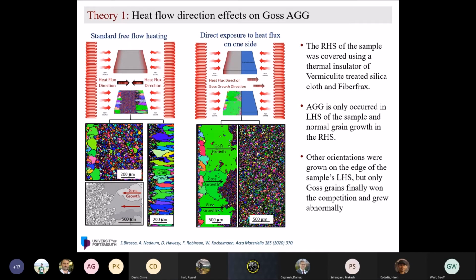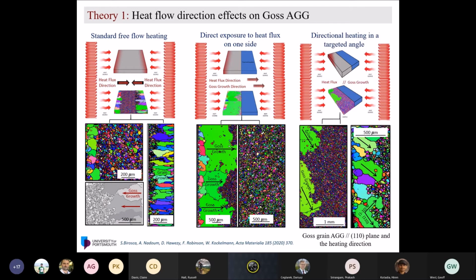And if we click one more, to prove that point again, we did directional heating at a targeted angle. We rotated the sample by 45 degrees, and we saw how the grain growth went through the 45 degree angle. We did a lot of slip trace analysis, as I will show you later, and this heat flux is actually following one of the six 110 directions. As you will see, the bottom green one is following two, and the rest are just following one of the 110 directions. Next.